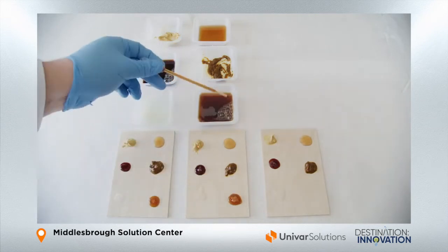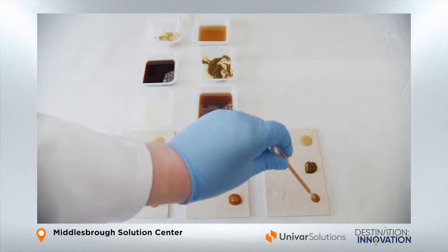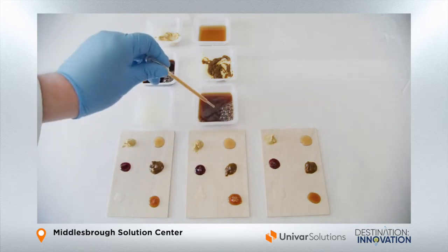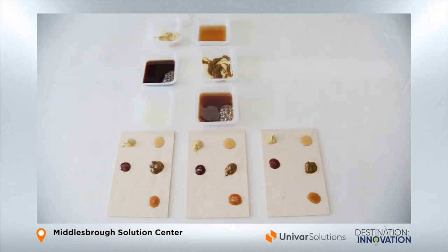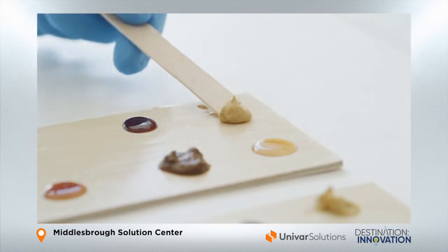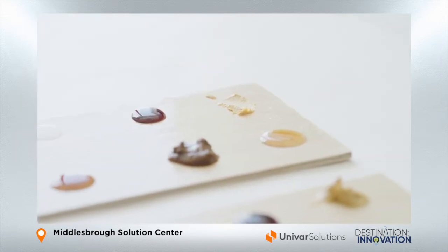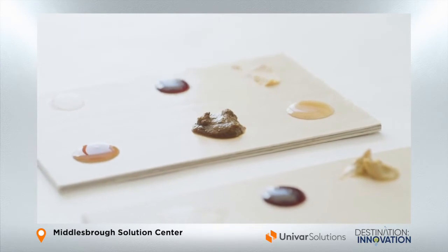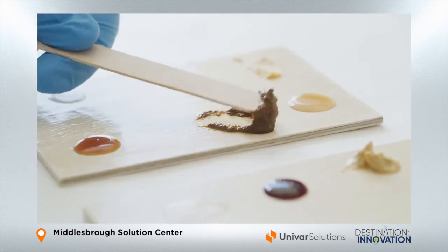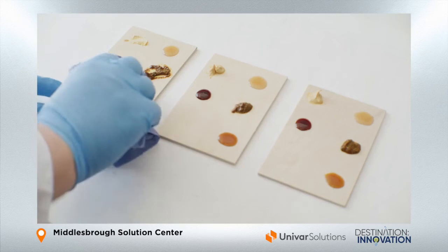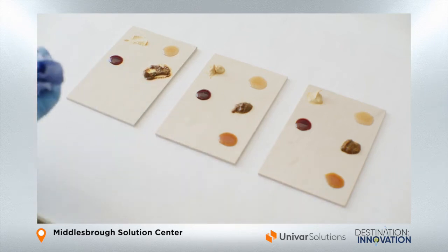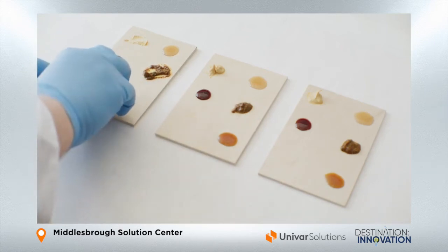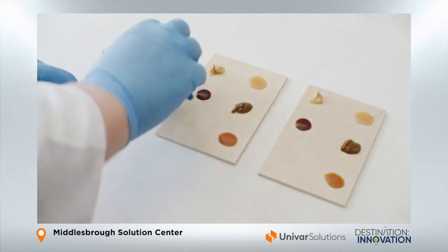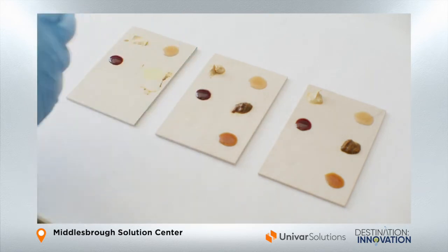In this test here, we've got 3 different coatings. The one in the middle is a standard acrylic product. The one on the left is an acrylic with a polycarbonate crosslinker, and the one on the right is acrylic PU hybrid. So basically for the test, what we actually did was prepared these panels, allowed them to cure, and then we placed the 6 common kitchen chemicals on the surface and left them for a set period of time. After that time had elapsed, we wiped these away and wiped down with water, and then afterwards visually assessed for staining.